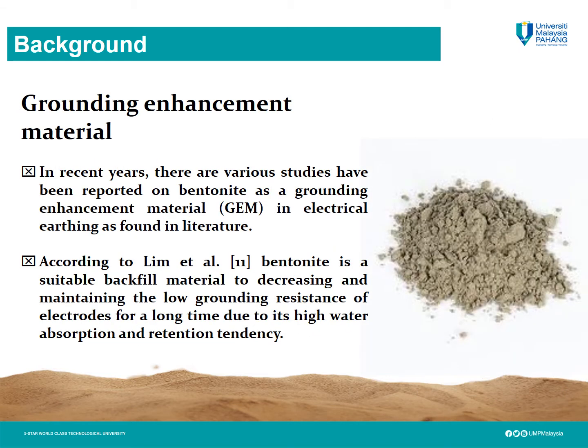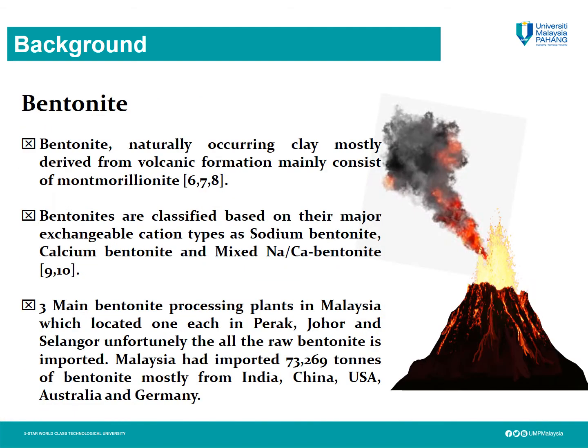In recent years, various studies have been reported on bentonite as grounding enhancement material, or GEM for short, in electrical earthing, as found in the literature. According to Lim, bentonite is a suitable backfill material for decreasing and maintaining the low grounding resistance of an electrode for a long time due to its high water absorption and retention tendency.